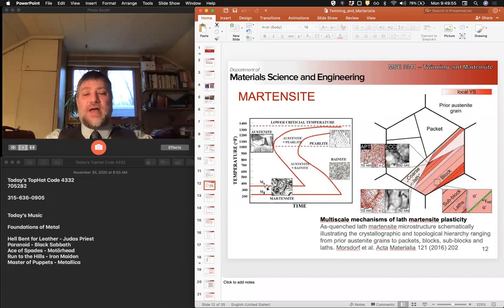We don't have to overcome an activation barrier for it to occur. Once the Gibbs free energy is there, it transforms. So we have a well-defined martensite start temperature, and as we keep lowering the temperature, we will create more and more martensite until we get to martensite finish, right? The TTT curve also shows us that we have to quench fairly quickly, right? Because if we cool slowly, we're going to nucleate pearlite. Or if we go a little faster, we're going to enter into the bainitic region.